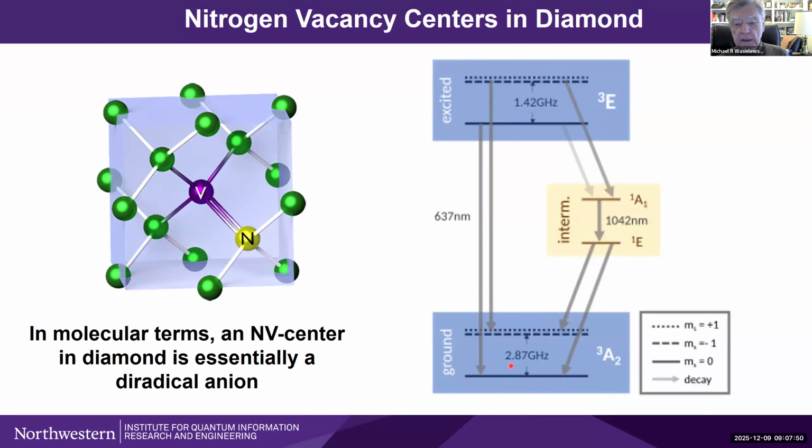So basically, by just doing essentially continuous irradiation with green light, you can actually get a highly spin polarized ground state. And then if you do spin manipulations on this ground state by simply executing transitions between that polarized state and the other two triplet levels, then you have the basis of a sensing element.